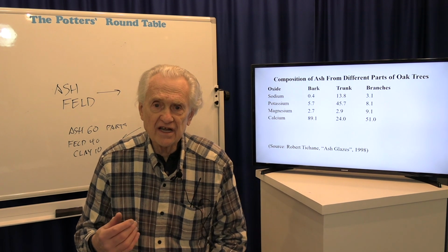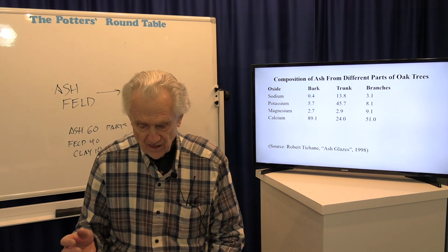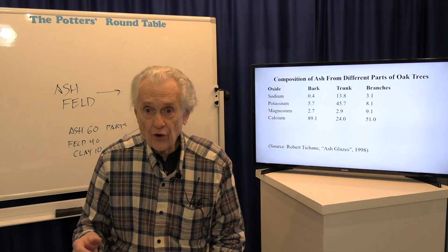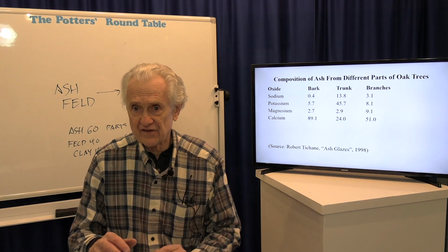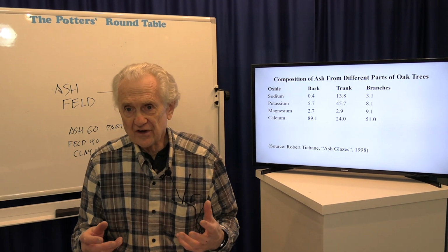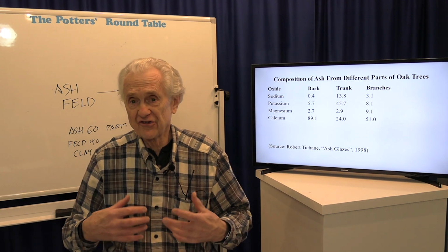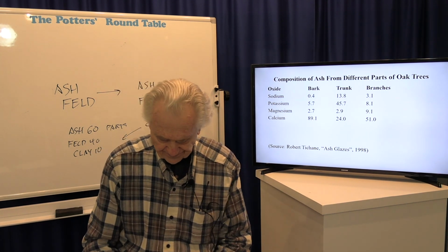And if the fired glaze looks too dry, too matte, then you could increase the fluxes, or reduce the clay, or also add silica. Because if it's not glassy looking enough, it means there isn't enough glass forming. So you could add the two things that would help make more glass: more flux to make it melt, and more silica to make more glass.